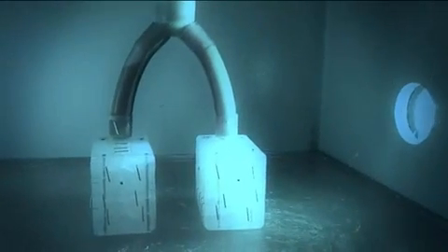From the tilting crucible in a vacuum chamber, the molten and stirred wax flows into the preheated silicone mold via a channel system. After the chambers are evacuated in order to obtain perfect filling of the mold, the pouring starts. The filled molds remain in the vacuum chamber until the wax begins to solidify.